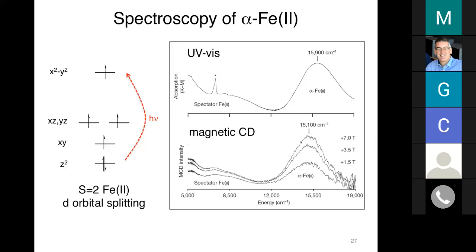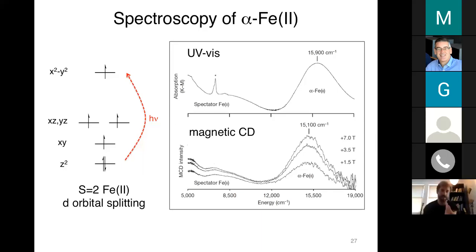It turns out that if that equatorial interaction was just a bit stronger, so that the x squared minus y squared orbital was raised just a bit in energy, you would actually get to an intermediate spin, or S equals 1, case. But in this particular ligand field, you're right on the borderline where the ligand field is strong enough that you get this very big equatorial-axial anisotropy, but not strong enough to destabilize x squared minus y squared so that it would become low spin. Oh, I see. Thank you. Does that answer your question? Yes, thank you. Okay, great.